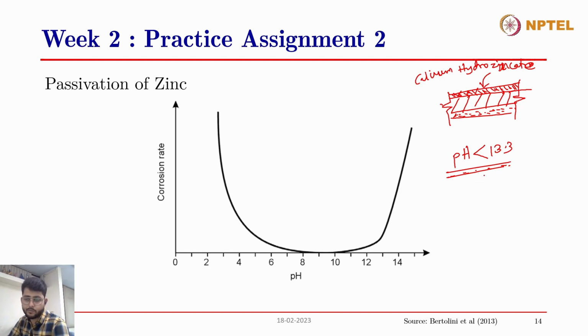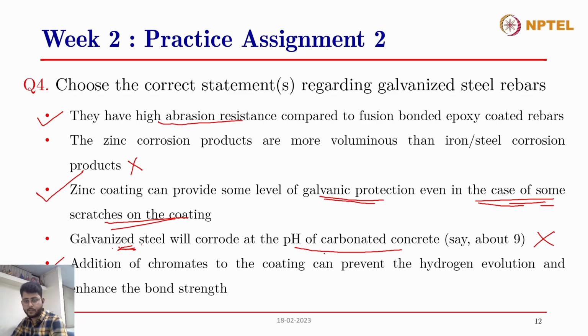But once the pH goes beyond 13.3, the corrosion products become coarser, and there is also the problem of hydrogen evolution, which might result in bond loss. But what happens at lower pH? As you can see, even at a pH of 9, the corrosion rate in the case of zinc is very low, even in fact at the lowest point. While normal steel can start corroding below a pH of, let's say, 9, the zinc layer over the steel can go below the pH of 8 or let's say 7. So this is the wrong statement that galvanized steel will corrode at a pH of carbonated concrete.